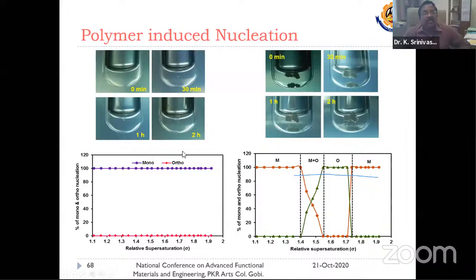And of course, this is a solution at normal conditions without any polymer templates. We adjust the relative supersaturation up to this range. We obtained only the mono. There is no ortho nucleation. Whereas in the presence of some polymer solutions, different polymorphs nucleated at different supersaturation conditions. So here the polymers induced selective nucleation at different crystallization conditions. So monoclinic, only orthorhombic, something like this.